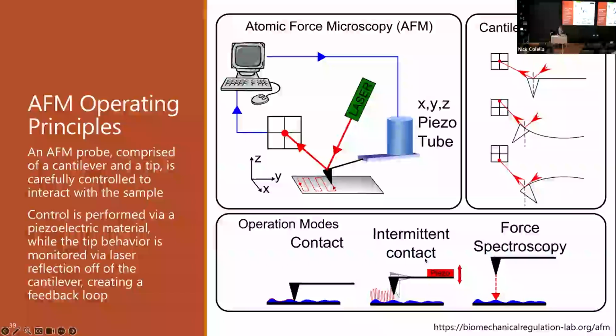We also have other AFMs in CNS, ones that are either intermittent contact, or what's called AC tapping, or contact mode. So if you just want the topography, these modes are a little bit easier. But if you want topography and mechanical properties, the force spectroscopy is really the best bet for you. We need to make sure that we indent just a little bit into the sample. If the cantilever is too soft, it just sits on the sample surface. If it's too hard, it just kind of stabs through your sample. So matching the cantilever is very important.